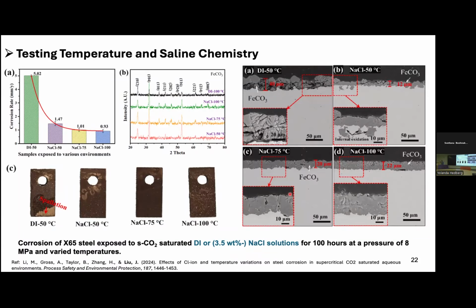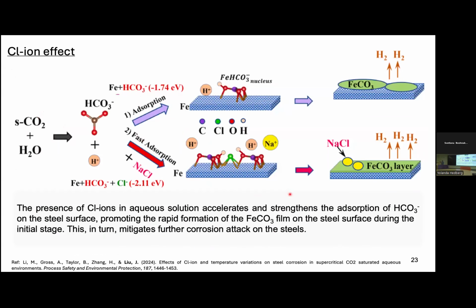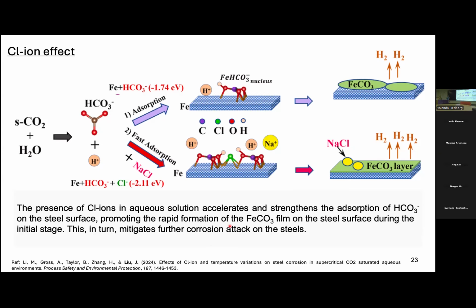Now, I'm not an expert in simulation to understand this, but over the years, we did some DFT calculation. Now, we had an editor give a seminar talking about it. Years ago, if you wanted to publish in Corrosion Science, if you just presented SEM and regular XRD, it was not good. Even though you can explain it, they still want to see the fancy TEM. So these days, if you want to publish, you look at all of those. Even though the DFT just gives you a number, they still want to see it. When we quickly review papers, you have SEM, you have TEM, not good enough. You must have some simulation result. I find this annoying, but at least for this point, they helped me understand why.